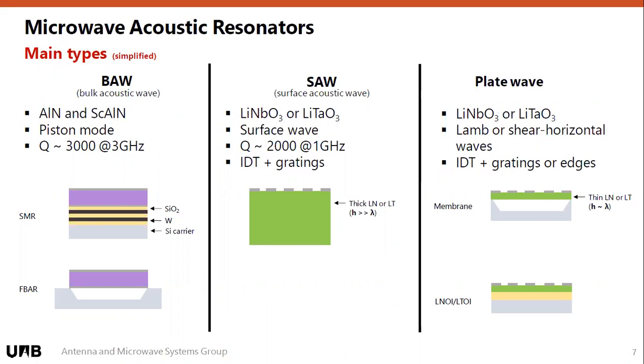You have BAW, the bulk acoustic wave, in which you have what is called a piston mode. It's a wave that is vibrating in this way. And you have two main types of resonators. Qorvo is doing the SMR, the solidly mounted resonator. So it's a thin aluminum nitride or scandium aluminum nitride layer mounted on top of a Bragg reflector made of low and high acoustic impedance layers, so that you have actually a resonance inside the piezoelectric material.